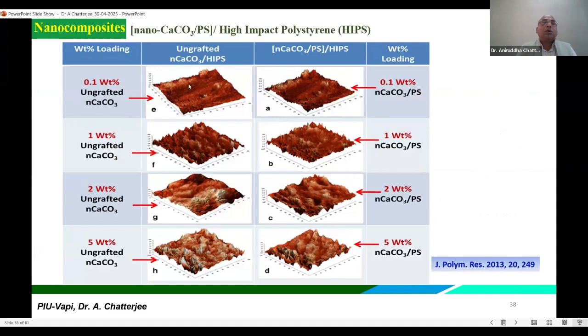Here are also AFM studies. Here you can see for the same percentages of loading, as the percentage of loading increases from 0.1 to 5%, the whiteness, the white color, is increased. Why? It is related to aggregated nanoparticles in the polymer matrix, whereas with the core shell structure loading you can see maximum dark color, meaning uniform dispersion of nanoparticles happened during mixing. This is the main reason that we are incorporating core shell structure instead of ungrafted or only silane modified nanoparticles in the polymeric matrix.